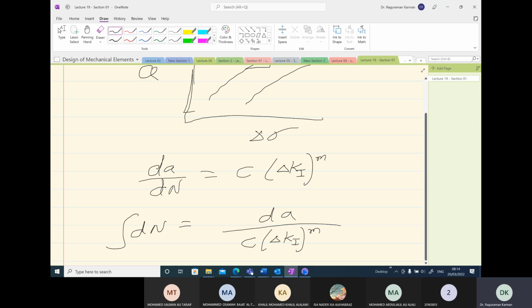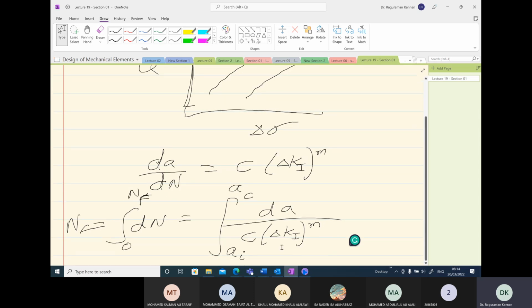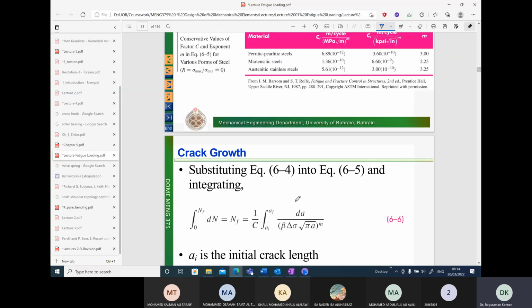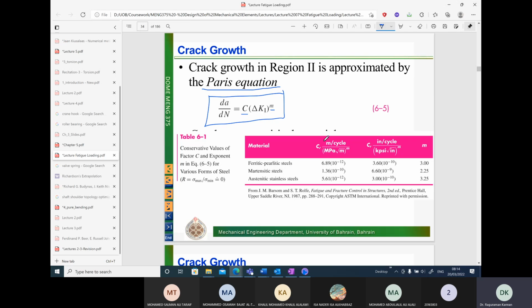To the power m, and then 0 to number of cycles to failure will give you the number of cycles to failure. And here will be the initial crack length, since we are integrating with respect to crack length, initial crack length to final or maybe critical crack length. If you know the critical crack length, then we can integrate up till the critical crack length, and the life of the specimen will be decided by that. Now the values of C and m are usually given in the problem.